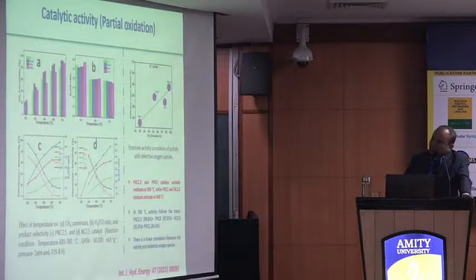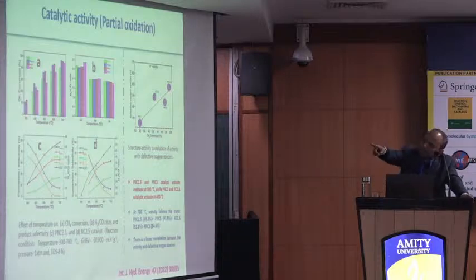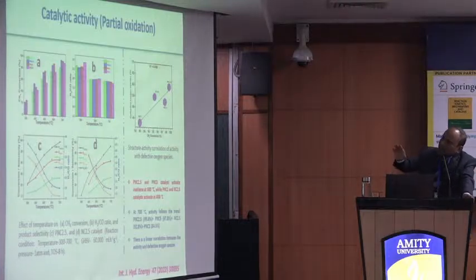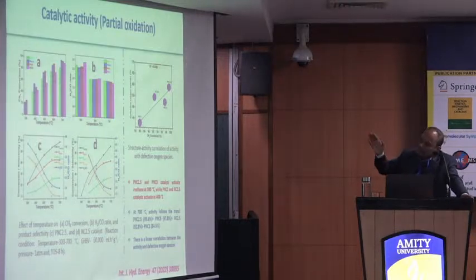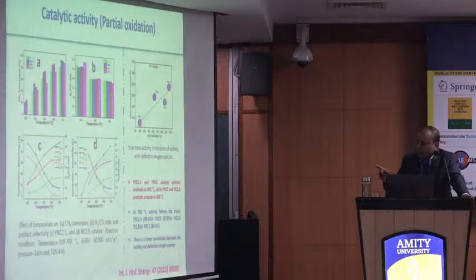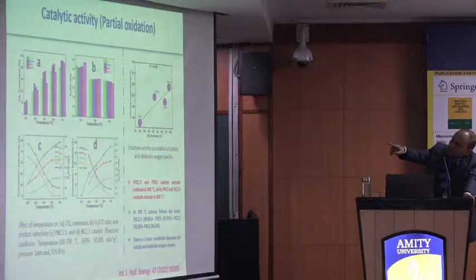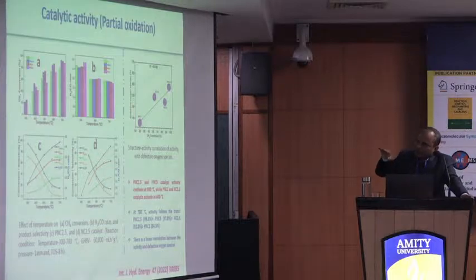This is the catalytic activity result. You can see that our catalyst is active even at a very low temperature: at 300 degrees it shows around 20% conversion. With increasing temperature the conversion increases, and at 700 degrees centigrade we are getting almost 100% methane conversion. And we can also see here that there is a linear relationship between the activity and the conversion.